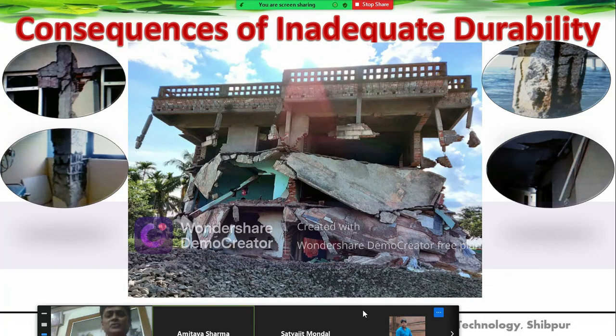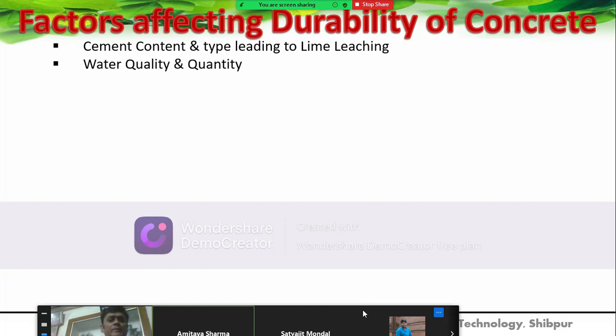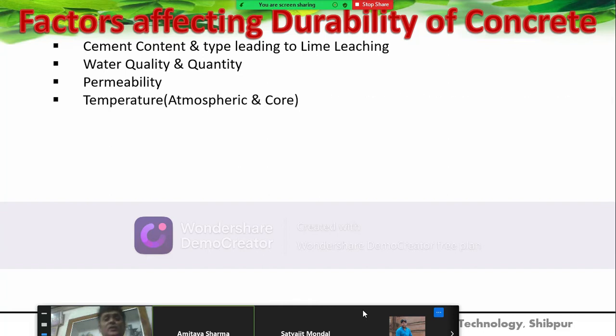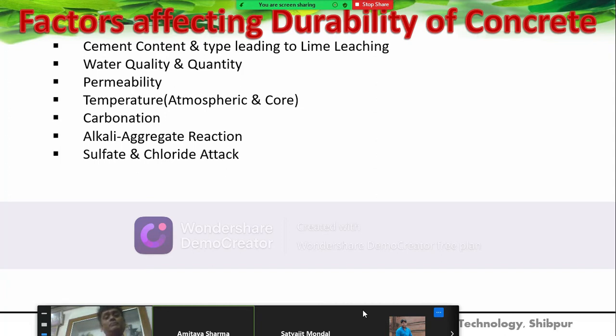In our locality you can see houses where columns have cracked, slabs are falling, and beams are broken—all due to inadequate durability. Factors affecting durability of concrete include: cement content, types of cement, water quality, permeability of water into the concrete—more permeable concrete means more in-durability—atmospheric temperature and concrete cover, carbonation of concrete, alkali-aggregate reaction where the stones react with the alkali calcium hydroxide in the cement, and sulfate and chloride attack, which is discussed heavily in this paper.